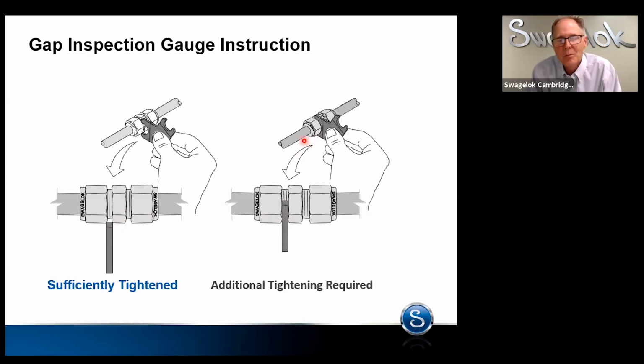What enables us to be gaugeable? It's a simple factor. It's the ferrules. It's the machining tolerances that we hold on our tube fitting. The ferrules, a lot of other manufacturers stamp their ferrules from tubing. Tubing has allowable tolerances of 1 inch and under, plus or minus 5 thousandths. You get a 2 ferrule fitting, you get 2 ferrules stamped from tubing, you've got 10 thousandths on one, plus or minus 5, 10 thousandths on the other, plus or minus 5.